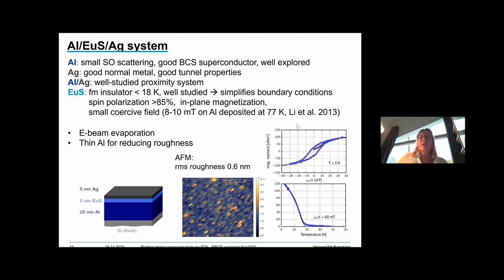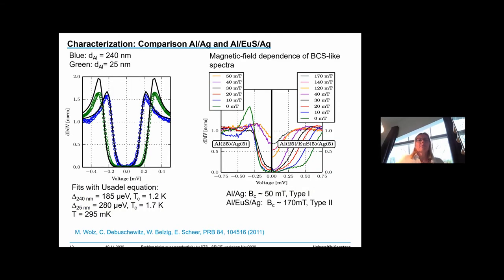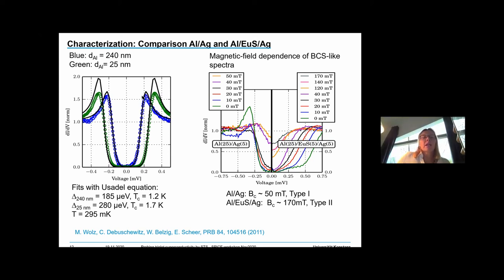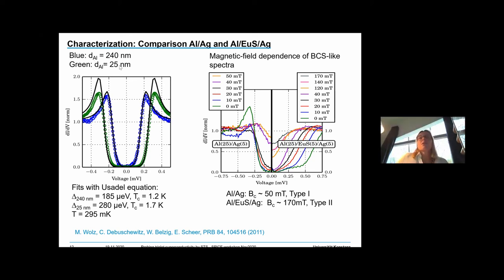We start with the Al/Ag system. Shown on the left are tunnel spectra for two different aluminum thicknesses: the thicker film (blue curve) shows the usual aluminum gap, with black lines as fits to the Usadel equation. When we make the film thinner the gap increases. We use this very thin thickness to get a smooth layer and better growth of the europium sulfide, and we characterize the spectra as a function of magnetic field.